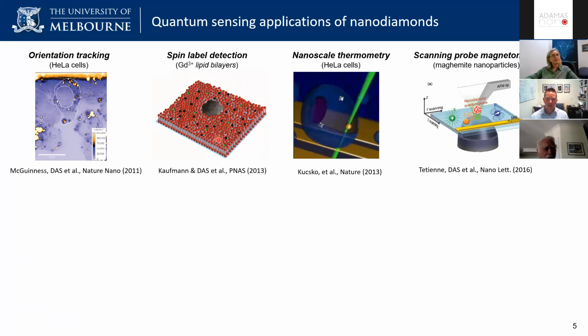Following that, we started to explore the idea of using T1 for detecting fluctuating magnetic fields and showed that with 15 nanometer nanodiamonds, we could embed those into artificial cell membranes that were labeled with spin labels. So in this work, we used gadolinium, for example. And using a single NV and a single nanodiamond, we were able to detect the presence of 2 or 3 atomic spin labels in these artificial cell membranes. And so that was a really interesting demonstration of the sensitivity of these sorts of systems, getting down to near single electron spins.